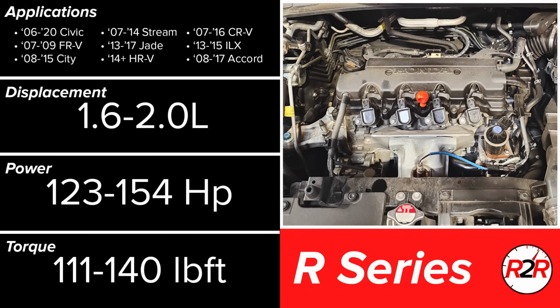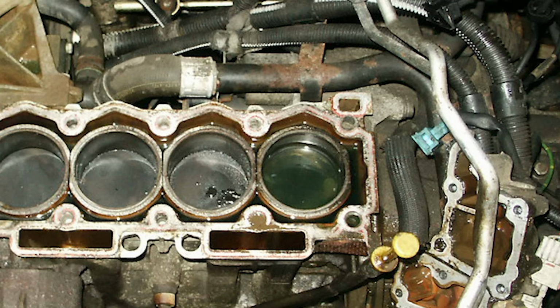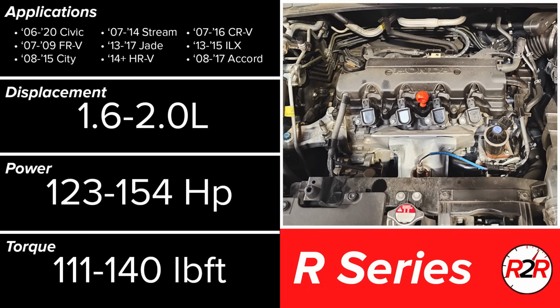When the early engines were made, an issue in the die design allowed voids to form within the material, not visible from the engine block surface. This resulted in many engine blocks cracking, as the internal voids would grow with heat and pressure. After the engine block cracks, coolant can leak out, allowing the engine to overheat. Quite often, this process would play out, leaving owners with a blown engine. While that doesn't sound particularly fun, the R-Series earns some credit, as Honda fixed the issue after 2009.